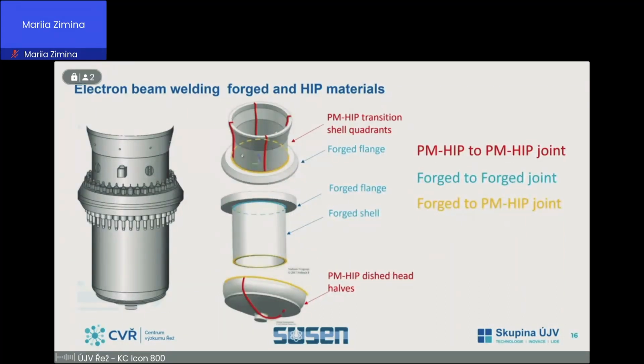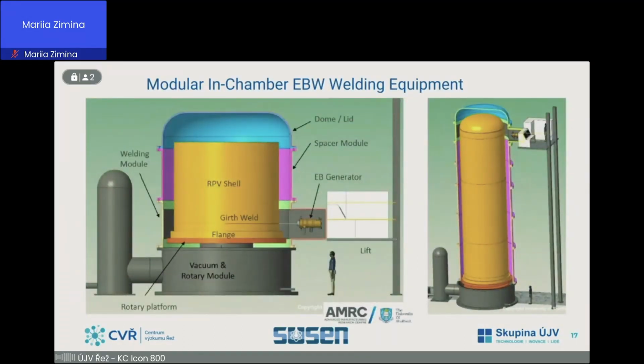Research in the Nuclear AMRC welding vacuum chamber has demonstrated that electron beam welding can provide an acceptable joining method for reactor pressure vessel materials, both forged and produced by powder metallurgy. The conceptual design of the device for welding the NuScale power reactor pressure vessel is in this picture. The design uses individual modules that can be stacked and destacked to form the vacuum chamber, wherein various sections of the small modular reactor vessel or other component will be assembled via electron beam welding.